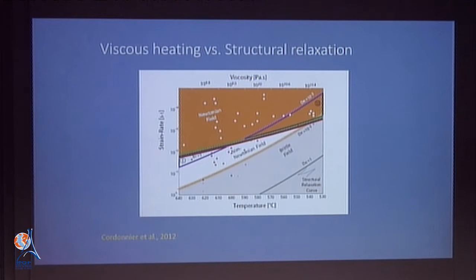And so the idea that you may go from one regime to the other at a temperature of about 600 degrees Celsius, where that green line crosses that blue line, gives us the potential of a remarkable playing field of these events in nature, because this temperature of about 600 degrees Celsius is something which we would see near or at the surface of these flows in nature. Okay?